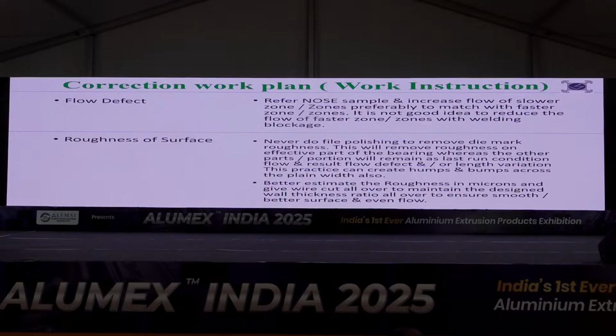When you have a flow defect, please refer to the nose. There, a flow defect must be due to faster flow or slower flow. So wherever you see there is a slower zone, say 3 sides are slower, 1 side is faster. Our die correction concept always goes for either direct welding on the die plate or bearings, or they reduce the die bearing elsewhere. You correct this way. It is not a good idea to reduce the faster flow. Better you increase the slower zone so that your extrudability and productivity go higher.